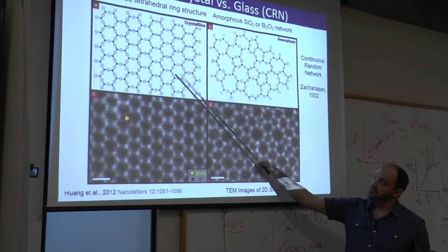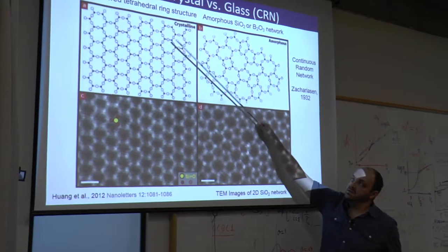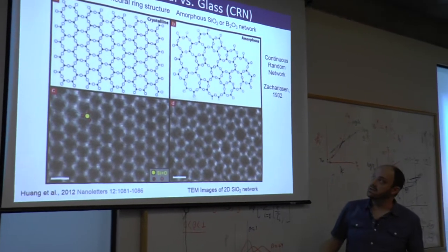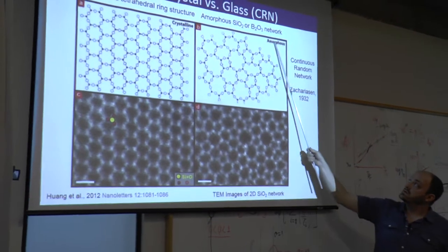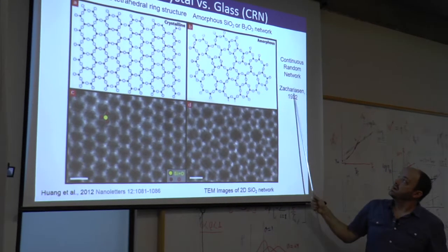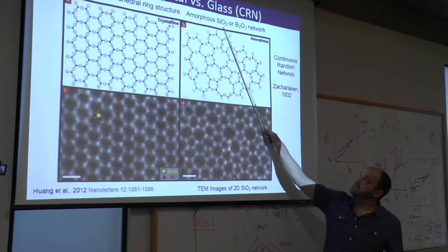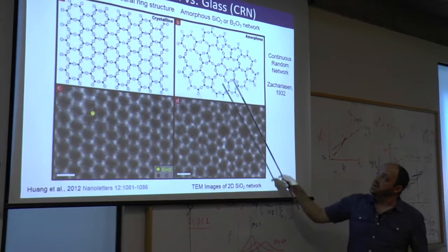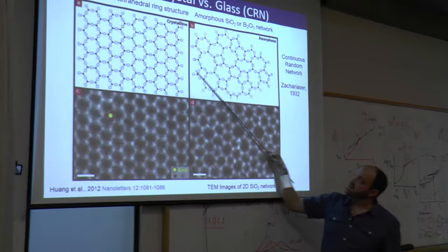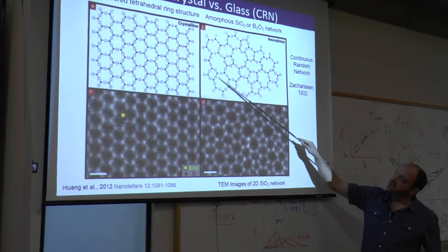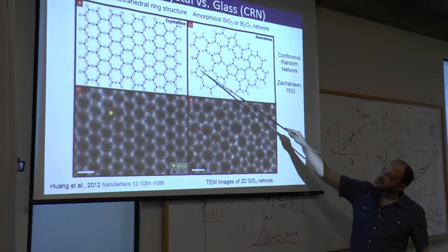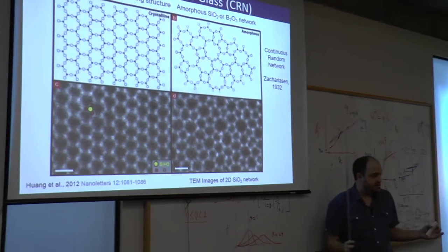But with minerals, you have a nice ordered system. This is why you get nice sharp diffraction peaks. When you go to an amorphous material or a glass, and Zachariasen was thinking specifically of SiO2 or B2O3, you have different distributions of ring sizes, and you have large voids and some small voids, and you get a wide distribution of these.